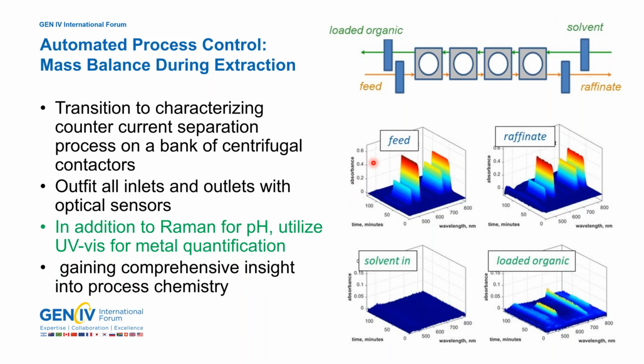We have neodymium in the feed, and we want to run the feed through a set of centrifugal contactors shown in the diagram here. The squares with circles in them represent the centrifugal contactors. We have a bank of 4 that we used. We ran a feed through the entrance of the centrifugal contactor, with the raffinate stream coming out the other side. We have counter current, a solvent that was run through to extract the neodymium to form a loaded organic phase.